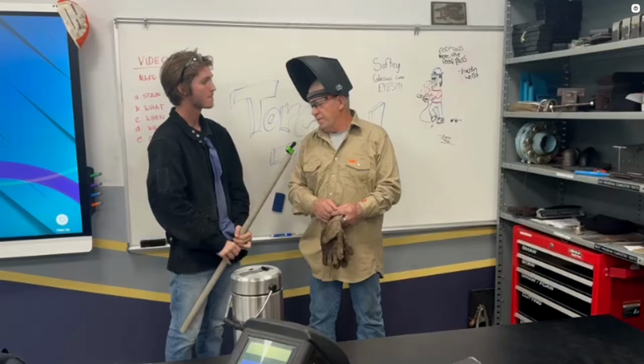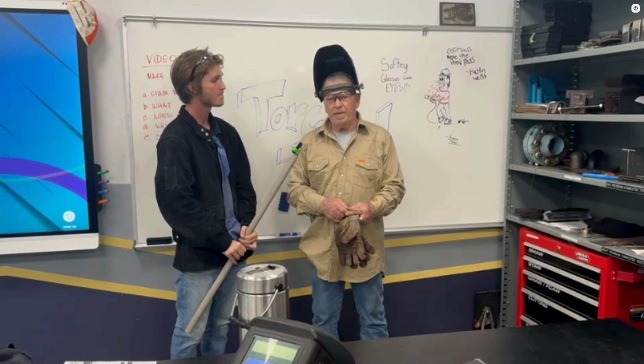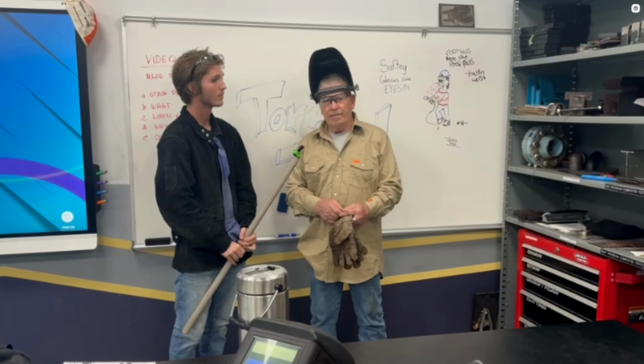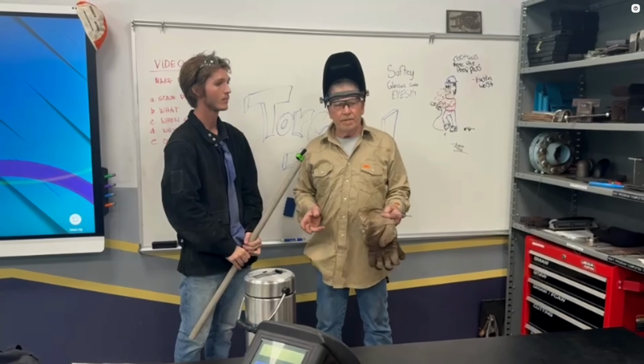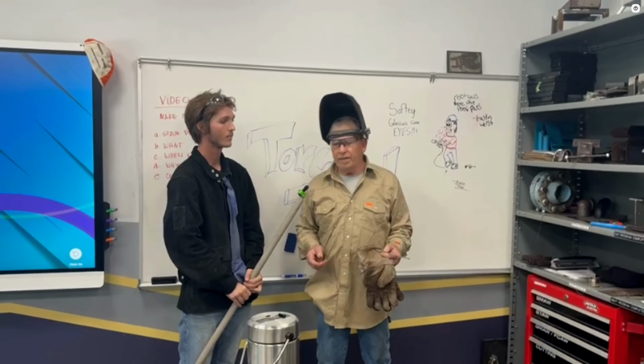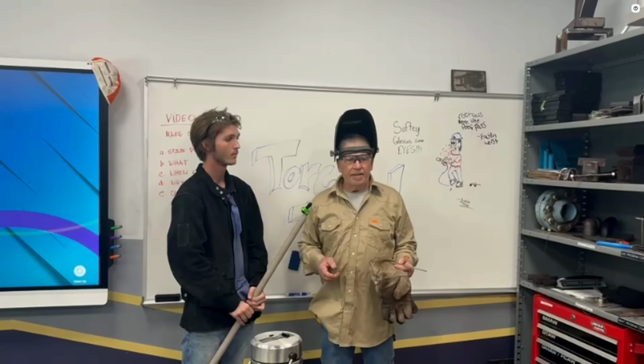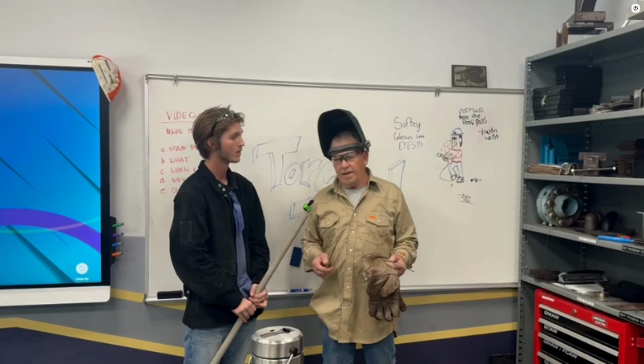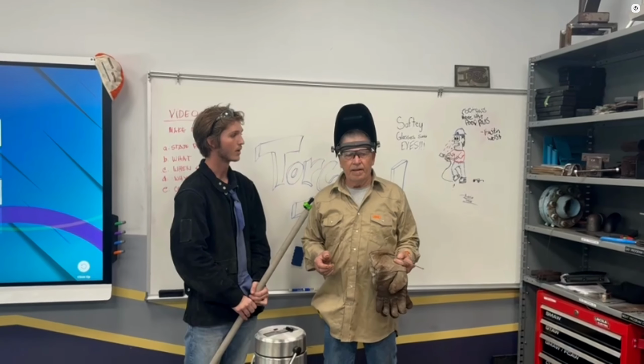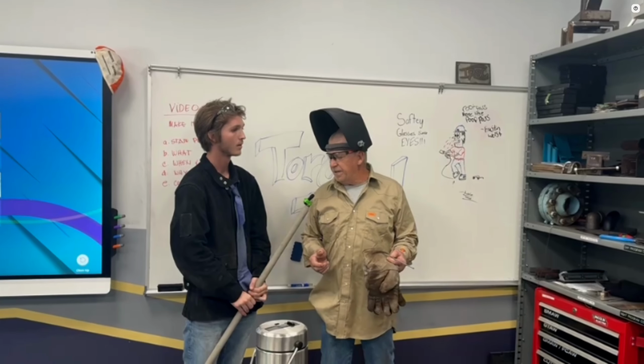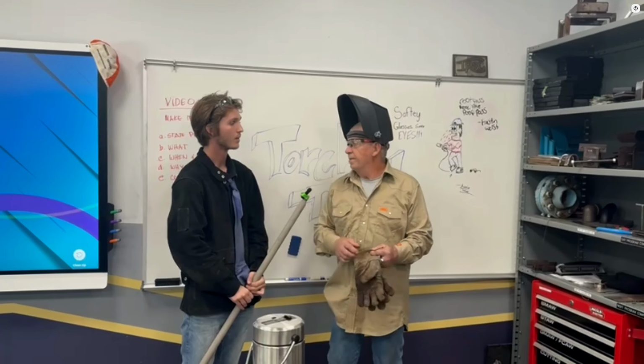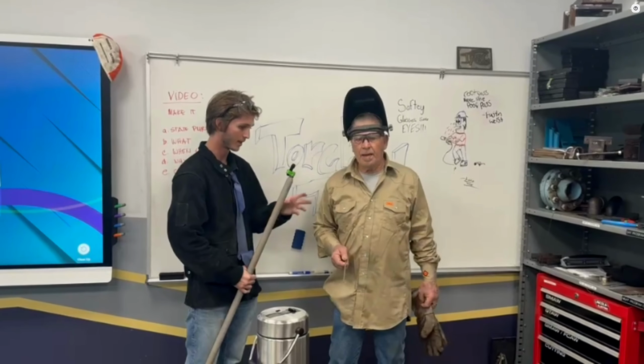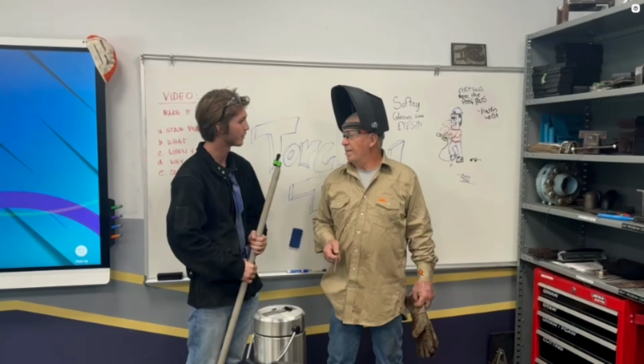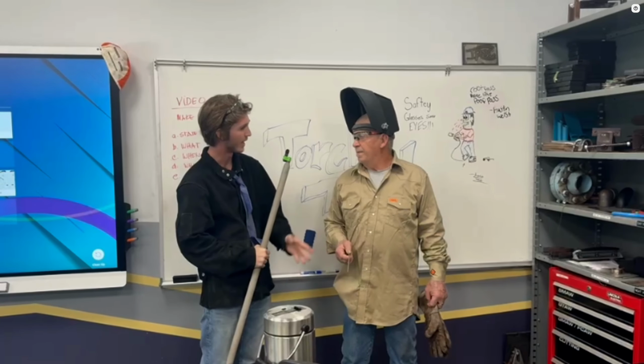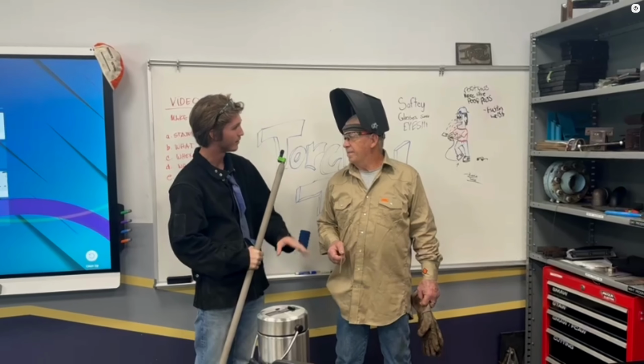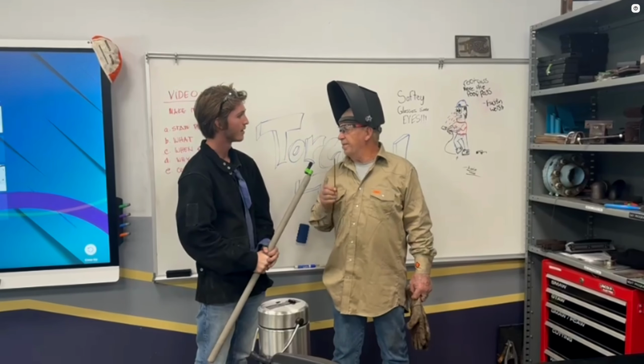So what are the different types of fillers, and what do they entail? It's basically how the molten puddle and the slag behave. So fast freeze electrodes, like 6010, 6011, solidify really quick. It makes them great for vertical and overhead welding because the molten metal doesn't drip or sag down. They produce a deep penetrating arc, perfect for root passes and pipe work. The bead can look a little rough and require more cleanup than others.